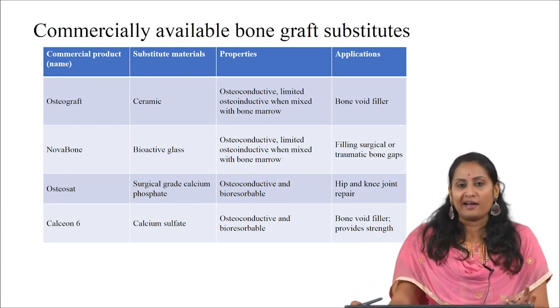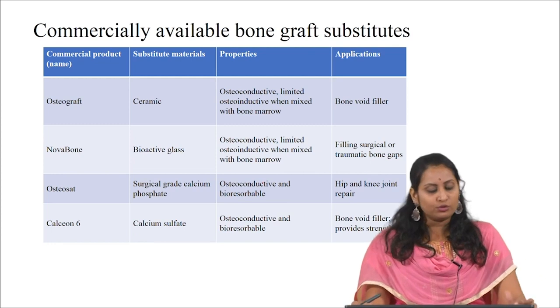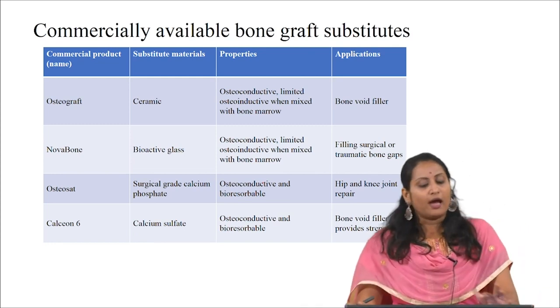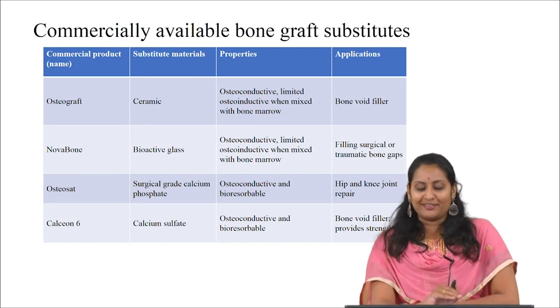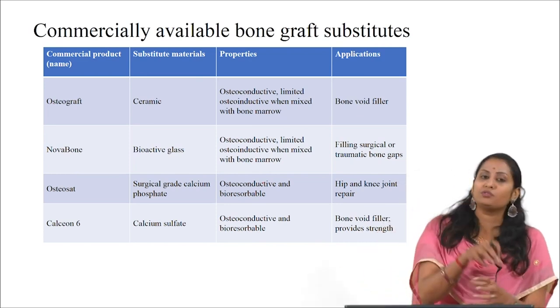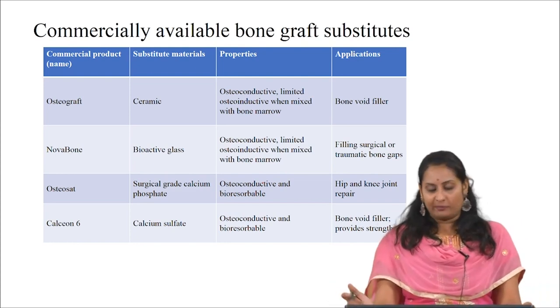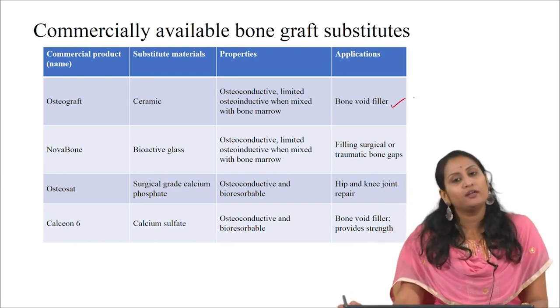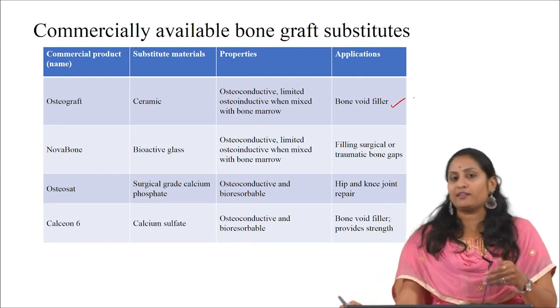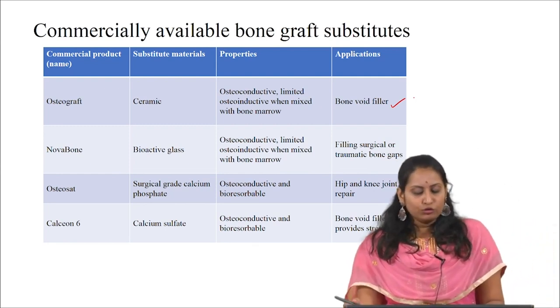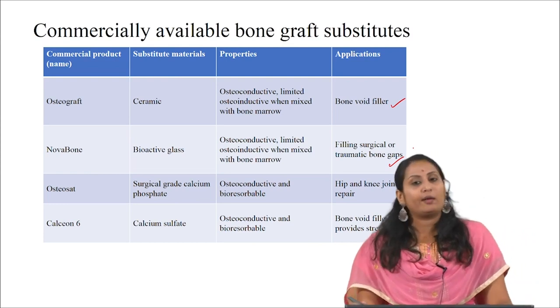Looking at commercially available FDA-approved bone graft substitutes: Osteograft is made of ceramic material, is osteoconductive, and becomes limited osteoinductive when mixed with bone marrow, which contains many mesenchymal stem cells — it is used as a bone void filler. NOVABone is made of bioactive glass (silicates), is osteoconductive, limited osteoinductive when mixed with bone marrow, and is used for filling surgical and traumatic bone gaps.